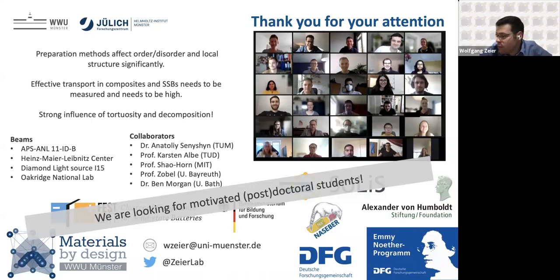Yeah, so for this chloride bromide iodide system, these are pure solid solutions. There's really no strain in the material, at least no macroscopic strain, put it this way. Locally, there can be. Strain is an important question when we talk about this whole quenching and different treatments of these materials. If you look at these Williamson-Hall plots, it doesn't look like we're inducing any strain by quenching it. So I'm not sure if they're actually strained in the sense of having macroscopic strain or microscopic strain, in the materials that I've shown here.